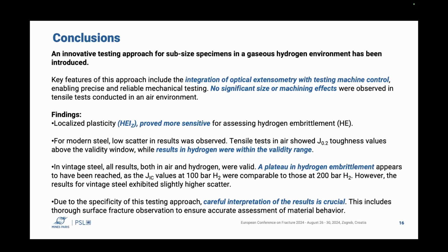We corroborate the works of our colleagues that the embrittlement index linked to the reduction of area is more sensitive to hydrogen embrittlement. And we can see also that the results with hydrogen for many toughness specimens are already in the validity range. Careful interpretation of the results is crucial because it's a new methodology.